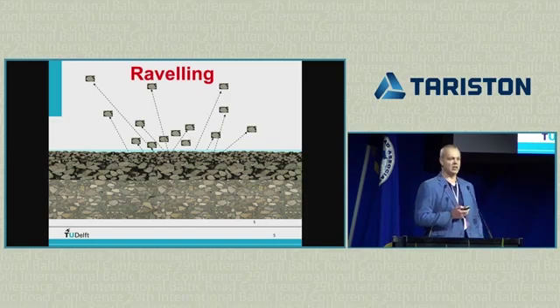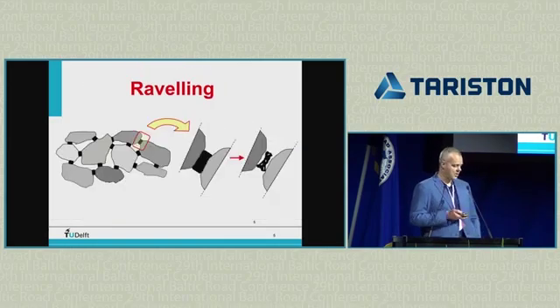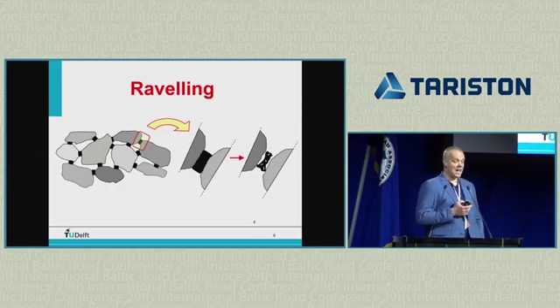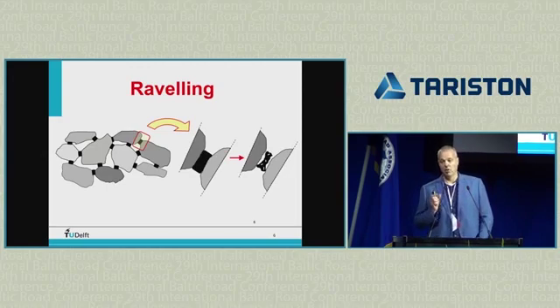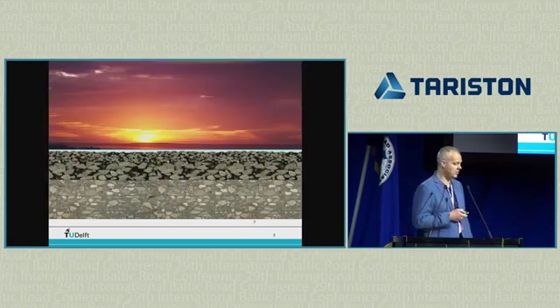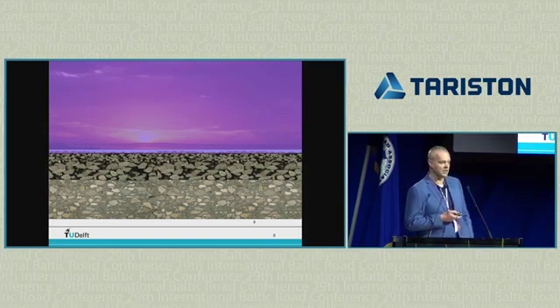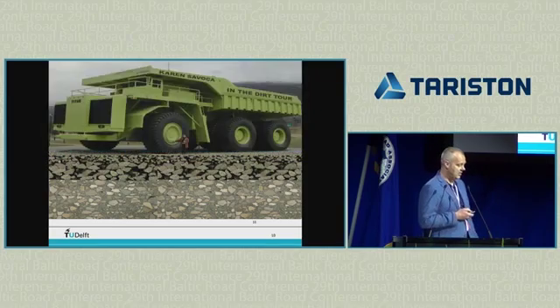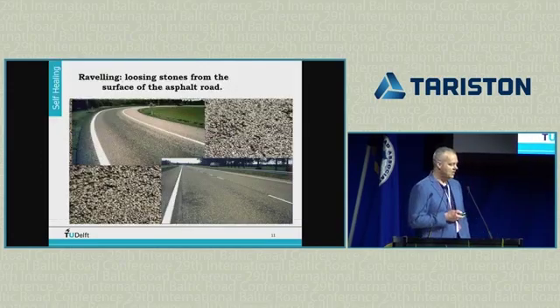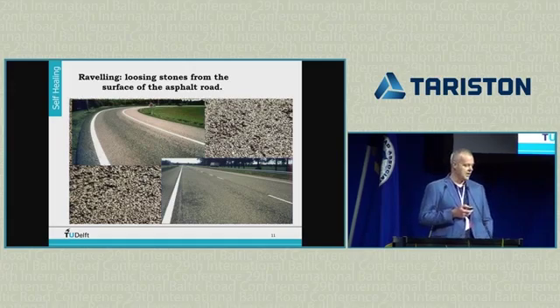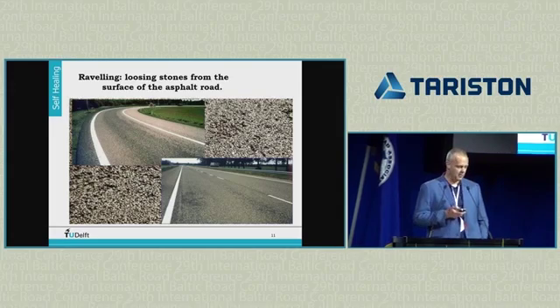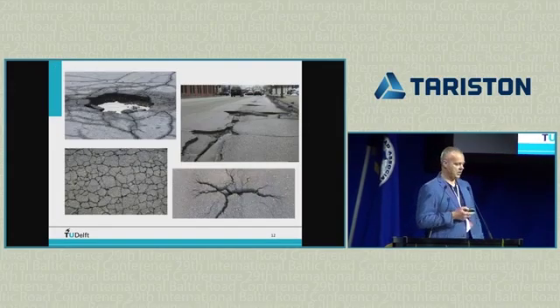For that, we developed a self-healing technology, which can be applied on all asphalt surfaces, actually. Raveling in this porous asphalt means that you have only a small amount of binder between your aggregates, as you see in this picture, and this binder will age, especially due to oxidation and UV light. This small layer of bitumen will become hard, it will become brittle, it will shrink, get micro cracks, and then delaminate from the aggregates. That's the system that causes raveling. So sunlight, and especially the UV light of the sun, together with some rain and maybe some snow, and some loading on it, then you will get raveling. It starts with some small stones coming off of the surface, as you see here, especially in curves. But then it leads to potholes, and this is what we want to prevent. These potholes we don't like.